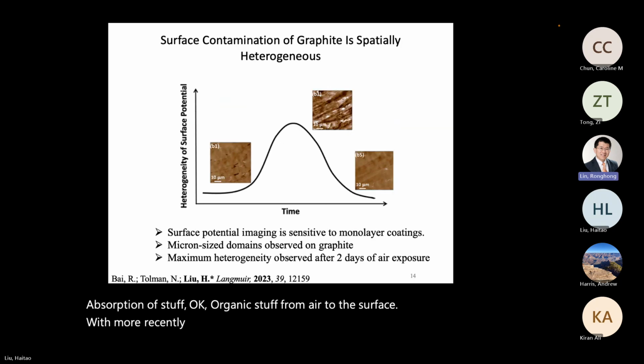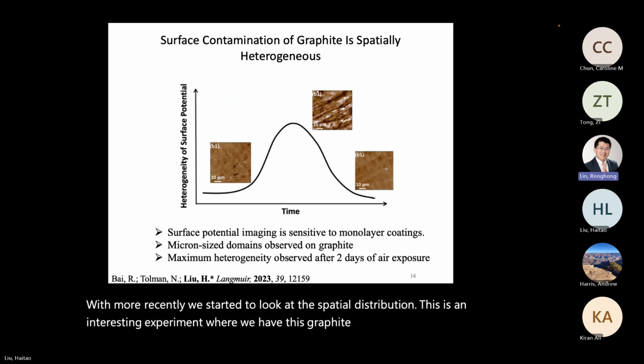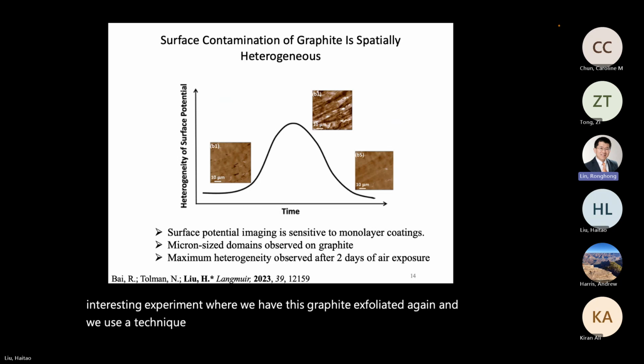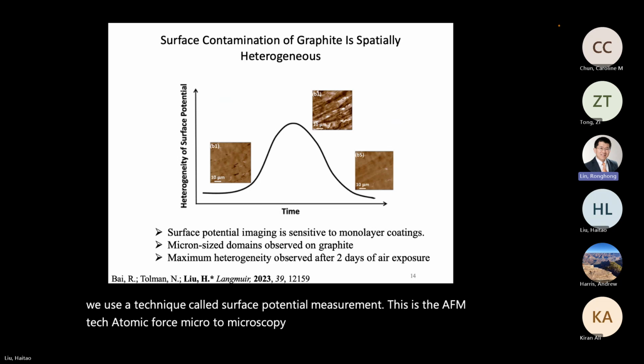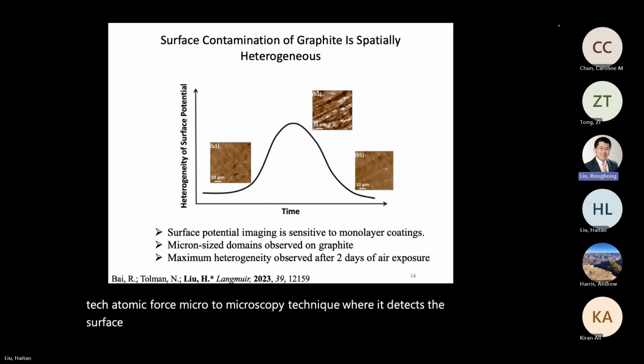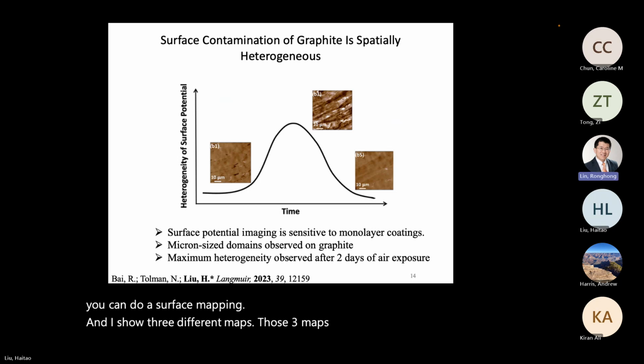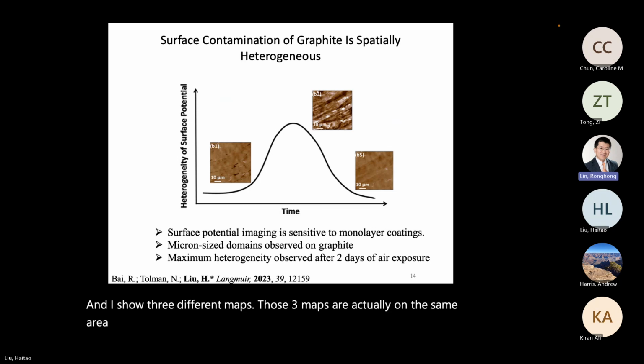More recently, we started to look at the spatial distribution. This is an interesting experiment where we have this graphite exfoliated again, and we use a technique called surface potential measurement. This is the AFM, atomic force microscopy technique, where it detects the surface potential. So essentially, that's the voltage, the potential of the surface, and you can do a surface mapping. And I showed 3 different maps. Those 3 maps are actually on the same area. Those are not topography, but rather the surface potential map.